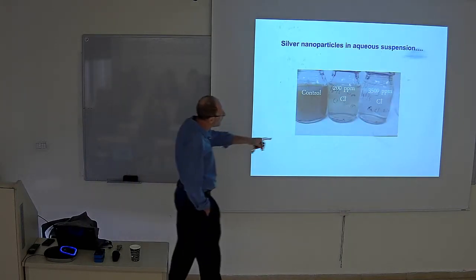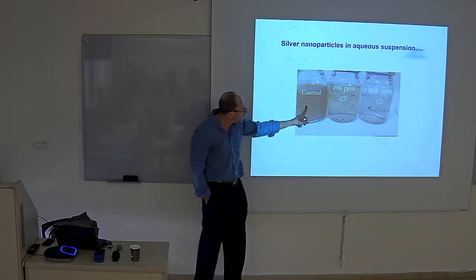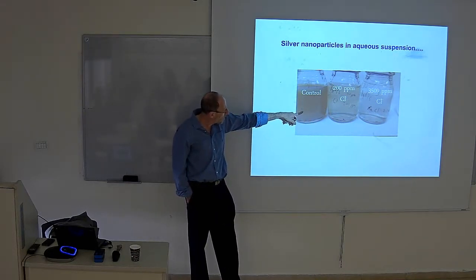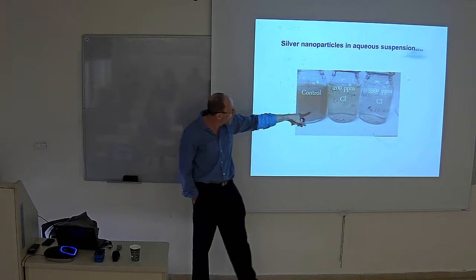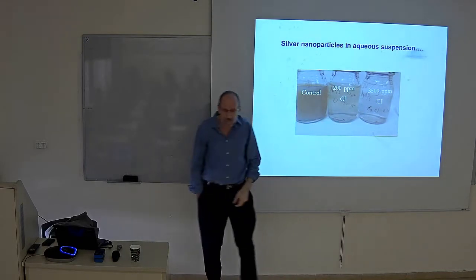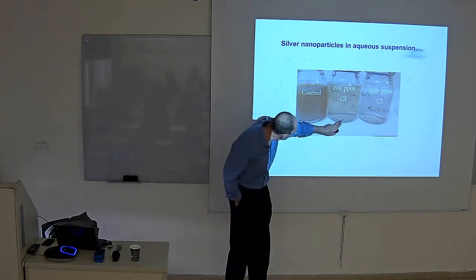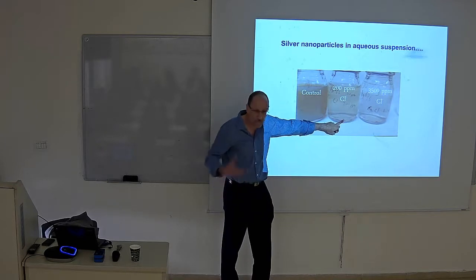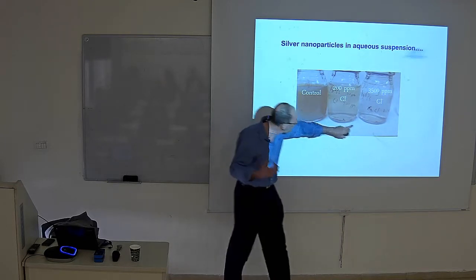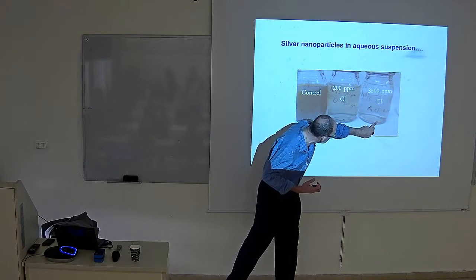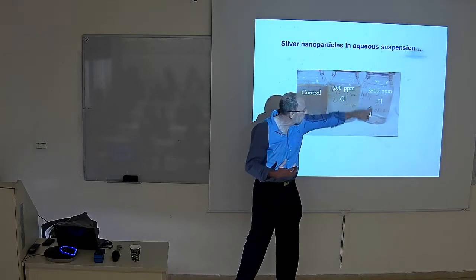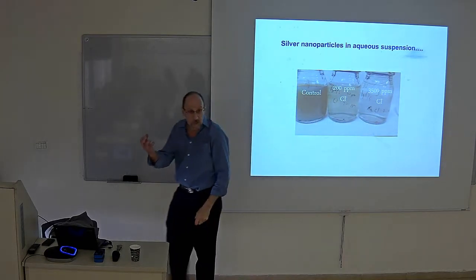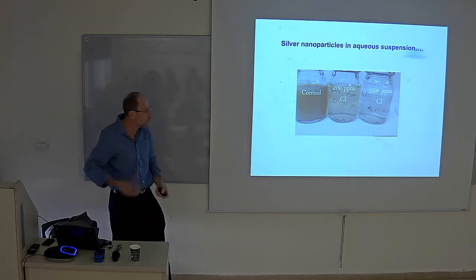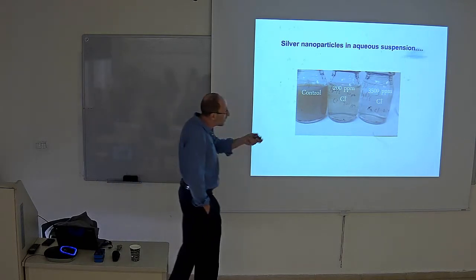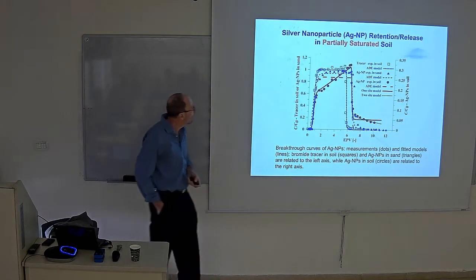One more thing just to show, we just did a simple experiment. Take a suspension of the silver nanoparticles, add increasing concentrations of salt, and here you can see there's actually a little aggregate of the silver that came out of solution, and here, it's very hard to see, here's actually the full aggregate. Essentially, everything comes out of solution because of the salt. Okay, so the presence of chloride has a negative effect in that respect.